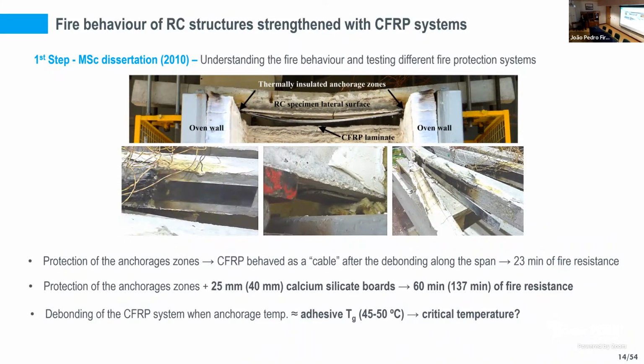So we did some fire resistance tests, where we tested beams strengthened in flexure with CFRP systems, and we concluded that if we protect only the anchorage zones of the system, the CFRP system was able to withstand load and to contribute to the flexural strengthening, even after the bond of the CFRP to the concrete was destroyed at the central point. So by protecting the anchorage insulation of the system, we were able to explore the contribution of the system by a cable behavior, as you can see. And with this system, only providing insulation at the anchorage, we observed that we were able to attain 23 minutes